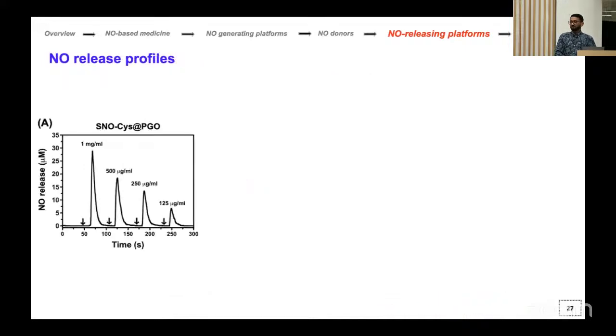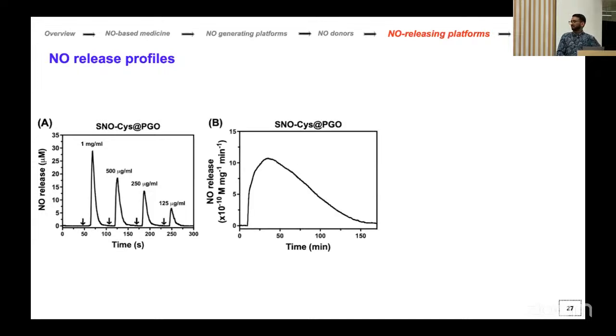And then the nitric oxide release profile with ozone-based chemiluminescence, first of all, to show the total release. If we use 250 microgram per ml of porous graphene oxide, we can produce around 15 micromolar of nitric oxide. So that's highly relevant. If we use 1 milligram, that could be a little bit toxic to the non-disease cells, but it is around 30 micromolar. This is a real-time release from 250 microgram per ml of graphene, showing how long we can produce nitric oxide. That's up to 140 minutes.